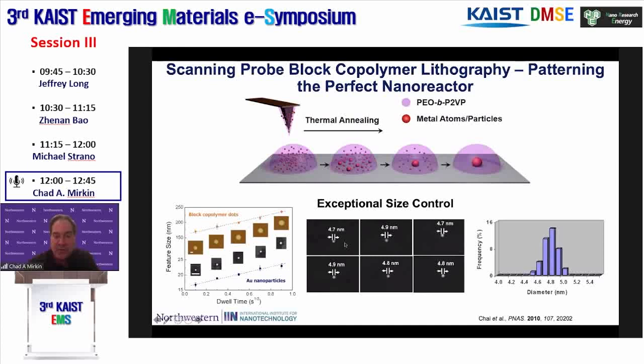If I reduce in size, I can reduce to tinier particles. Here you can see we're making gold particles that are 4.8 plus or minus 1/10 of a nanometer. I use that number and cite it because we've made millions of these using the polymer pen type system to generate millions in parallel. And then we can get histograms like the one shown on the right.